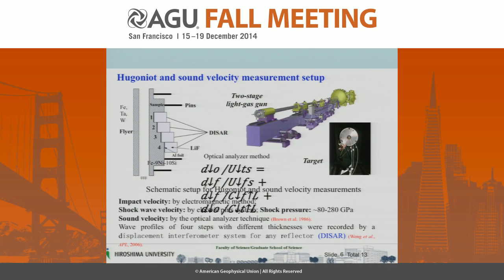A series of experiments were designed and conducted using a two-stage light gas gun up to a pressure of about 280 GPa. This is the schematic setup of our Hugoniot and sound velocity measurements, showing the flyer and target. We used iron, tantalum, and tungsten as our flyers. The impact velocity was measured by an electromagnetic method, and the shock velocity of the target was measured by pin systems.